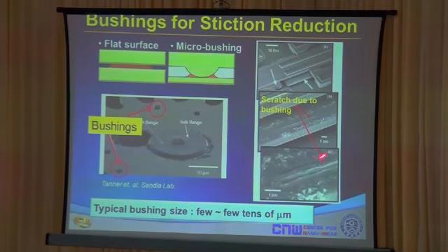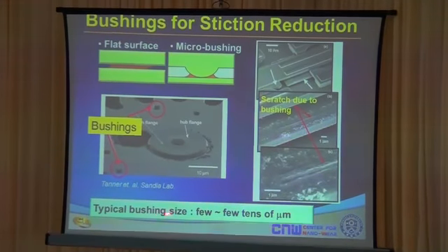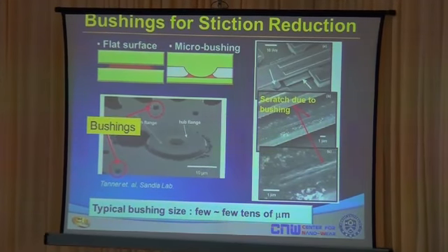This similar design was used in the landing zone that I introduced earlier on hard disk drive disks. The problem now is that these bushings that are fabricated on MEMS components wear out themselves. And these images show you that these bushings are severely worn out with operations, and these bushings are in the size of a few to a few tens of micrometers. So in this study, what we want to do is to quantify the wear of the bushing and compare the wear with that of the AFM tips.